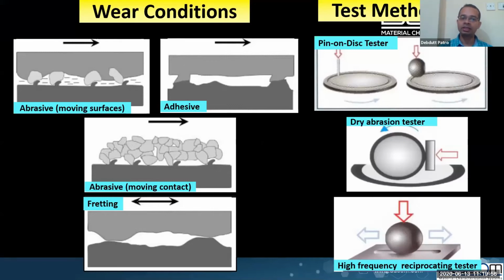Now we'll quickly look at when these asperities are contacting against each other. There are two scenarios. One is where there is solid to solid contact. Then you get wear, dry wear, and then we will have liquid, which is put as a lubricant, and there you will have liquid lubricated wear. So these images show the dry wear conditions. You would see the surfaces rubbing against each other, and if in case there are certain debris or sand particles, let's say, which come between these moving surfaces, they can act as abrasives, and wear out both the top and the bottom surface.